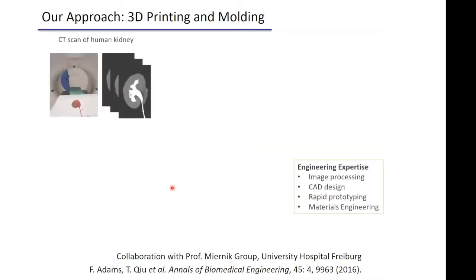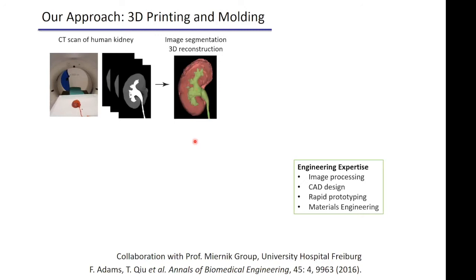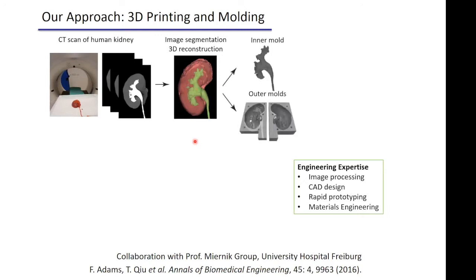Basically, out of a lack to test our own devices that we were developing, we started this, and we started with human cadaver organs. So this is a real organ that we can then scan with very, very high resolution, because of course it's no longer alive, and we can use contrast agents to get very good 3D models of organs. And these we can stitch together and get a computer model of the organ. And then we can resort to 3D printing, but not to print the tissue, but to print the outside and the inside, basically the molds. And this then allows us to use these fabrication techniques to get the structure right.